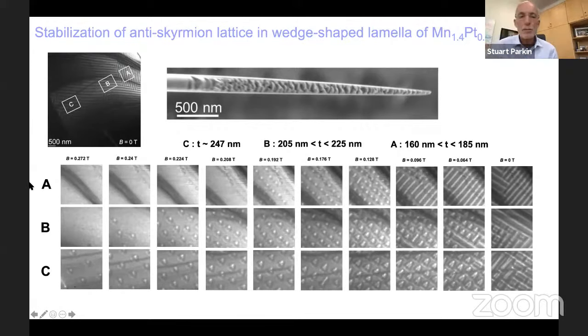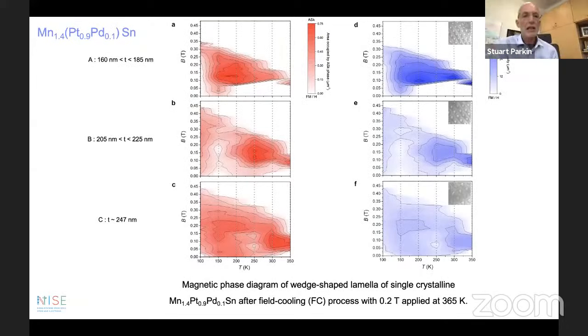Now, depending upon the thickness, the phase diagram can evolve. That's what I want to discuss in a little bit more detail. And in particular, I want to first make the point that what's really nice about the anti-skyrmions in the Heusler compounds, we've seen it in several different Heusler compounds, is that as a function of temperature and magnetic field, they're very stable. So over a wide range of perpendicular magnetic field and a wide range of temperature, you can stabilize arrays of these anti-skyrmions. This is what is shown here, showing you that as a function of increasing thickness from 160 nanometers to 1/4 of a micron, the phase diagram is such that the stability of the anti-skyrmions increases. That's what I want to briefly mention here.